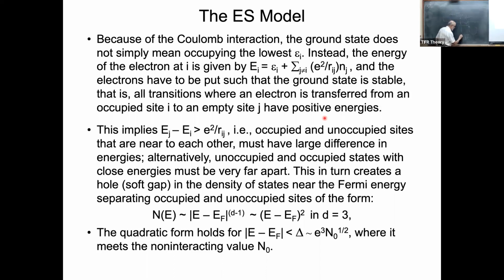In the insulator, he's saying you actually have a parabolic gap in the density of states because of Coulomb interactions, and it doesn't matter how small they are. If the Coulomb interactions are small, you'll get a gap that's smaller, but the density of states at the Fermi level is always going to be zero. That's consistent with what was seen in the tunneling data, right? Density of states was going to zero at the metal-insulator transition, and it's certainly consistent with it remaining zero in the insulating phase.